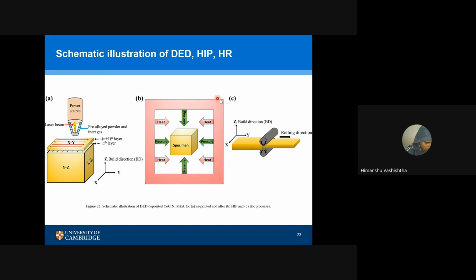Then we did hot isostatic pressing sintering, and then a hot rolling process. So we first printed a sample, then passed it through two different stages. One set of samples we collected here, then a second set of samples we collected there. Now we'll try to compare what hot isostatic pressing is doing versus what hot rolling is doing.